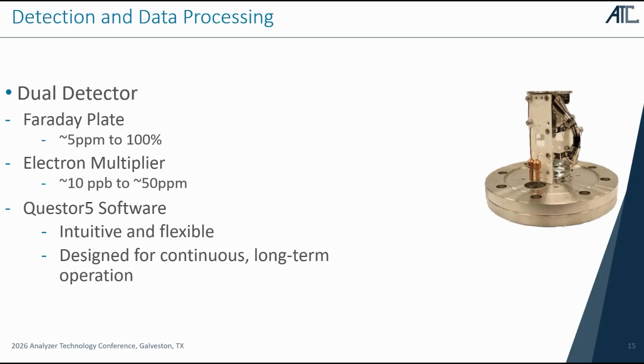It's usually a 1-for-1 ion to concentration type of arrangement on the data acquisition and processing, versus an electron multiplier, which has a detection limit of single to double-digit ppb and is usually good to about 50 to 100 ppm. These do work in conjunction and can switch from one to another if there's a large release going beyond that. An electron multiplier amplifies the signal, so there's usually somewhere between a 500 and 1,000-fold increase in the signal, so you get a very clear signal at very low levels using the electron multiplier versus a 1-to-1 Faraday plate, which is good for high concentrations, but not necessarily low concentrations.